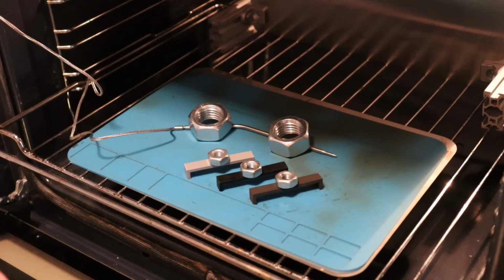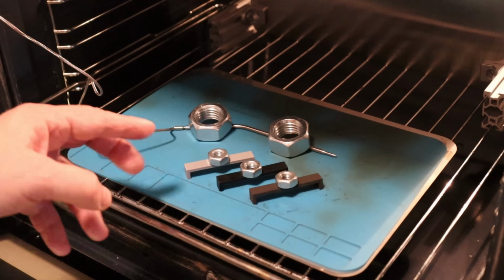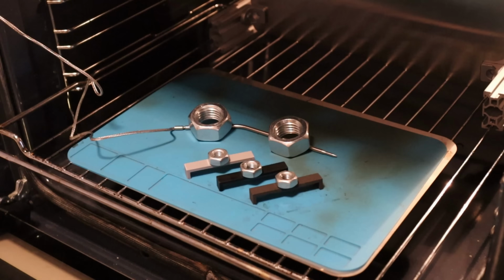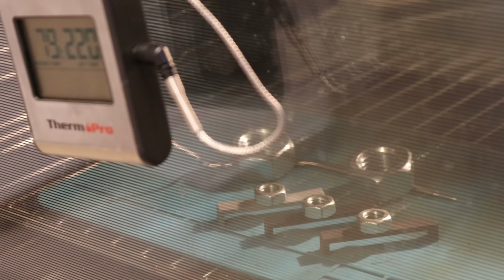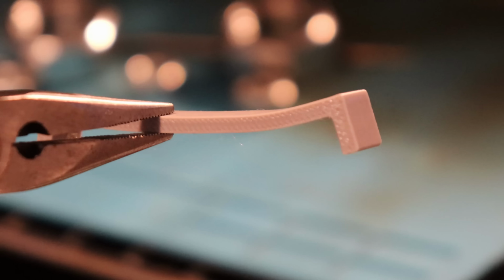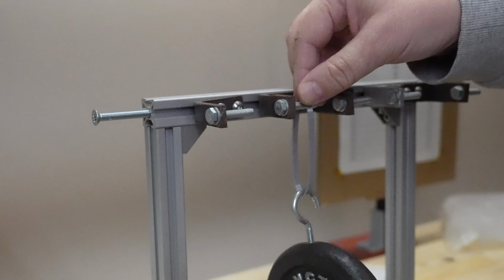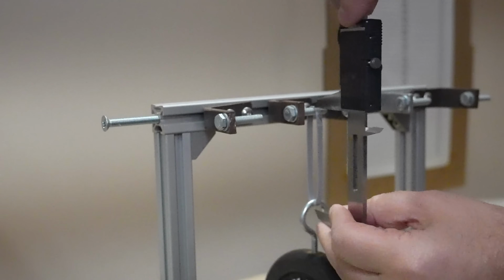Temperature test in the oven, and I always have several tests in progress, but maybe some of them I have to take out earlier. This is speed up video, and TPU 95A started to deform at 86 degrees Celsius approximately. Here this was 80 degrees. Well, I can see some permanent deformation on this TPU, but now when it's cooled down, I think it has similar hardness or elasticity.